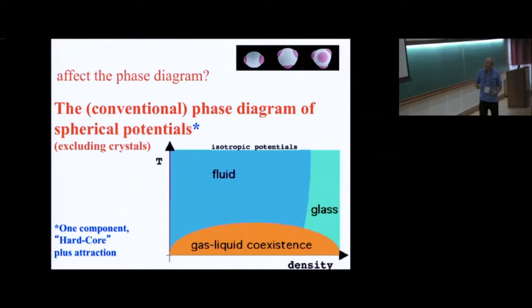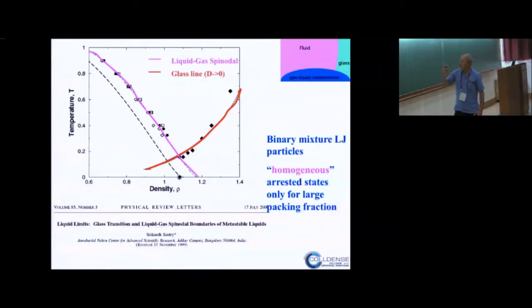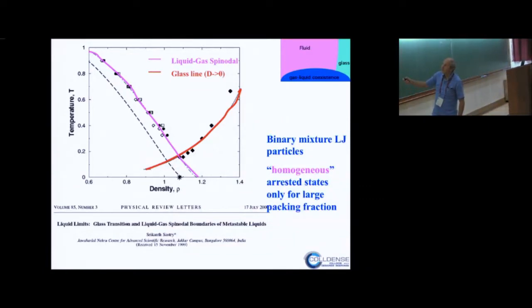And indeed, this idea was already studied a long time ago by Shrikant in this article on a Lennard-Jones system, where he studied theoretically and numerically the intersection between the glass line, you see here, and the gas-liquid spinodal. So in some sense, he was able to detect what is the lowest density at which you could, in principle, form a glass in this Lennard-Jones system. So there would be no possibility to form homogeneous glasses, let's say. You can always get phase-separated configurations in here, but homogeneous glasses for density lower than that. And at the same time, you cannot answer the question of how this Kauzmann line, this glass line, ends up if I go to lower densities?